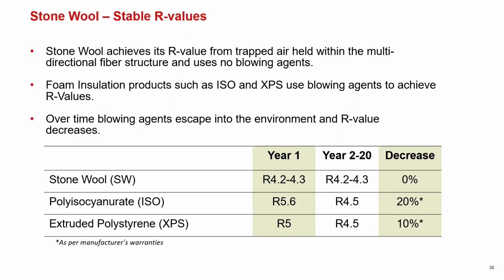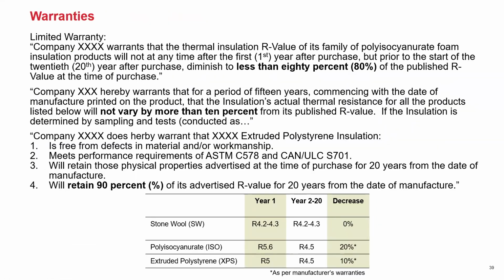And so now when you start to compare that to some of the foam insulation products on the market, in particular polyisocyanurate or XPS, which do use the blowing agents, as I mentioned before, they will off-gas over time, which is not great for a variety of reasons, but from a thermal perspective, you'll see a drop in nominal R value with polyisocyanurate. You'll see a drop of up to 20% sometime between year 2 and 20, and with extruded polystyrene, it's about a 10% drop, which doesn't drop them to awful levels by any means, but it might not be what you're expecting from the specification side. And as we're looking at making sure that these buildings are performing to our expectations, for more than 2 years, we want to make sure that we understand what the long-term performance values are of these products. And it shouldn't be a surprise. It's in the warranty terms for a lot of the manufacturers of the rigid boards, but it's just something to be aware of when you're looking to specify products.